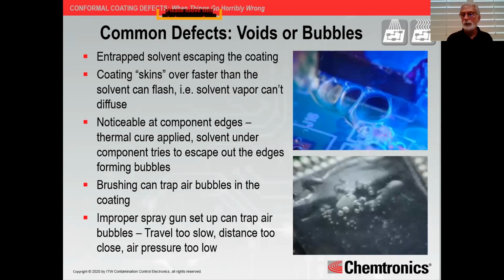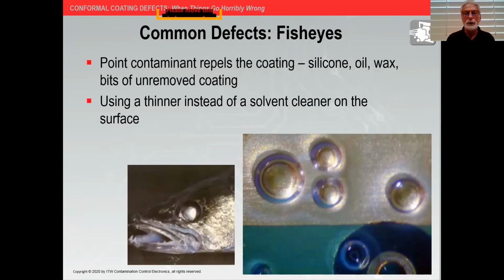Now, I did include, no, go back, please. I did include this last one, using a thinner instead of a solvent cleaner on the surface. If you're cleaning an area, especially a rework area, don't use the same thinner that you're using for your coating if you have a selective spray system or a spray gun, because sometimes that is not the proper solvent to clean those residues. And what that ends up doing is now you just smear that residue around that area. It just doesn't properly dissolve and remove a lot of these contaminants. So please be aware, those are other causes of fish eyes.